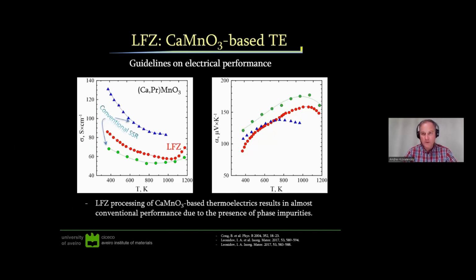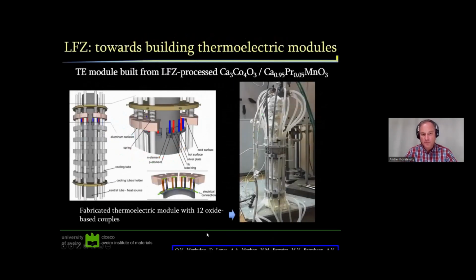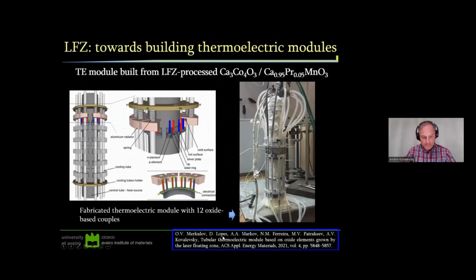In fact, we are thinking about using the laser itself for post-thermal treatment without melting our material. Nevertheless, the advantages of laser processing, like crucible-less fast processing, although in many cases we still need post-thermal annealing, we consider these advantages quite important to try to build a module based on this laser processed material. This work was performed with our colleagues from the Institute of Solid State Chemistry from the Russian Federation.